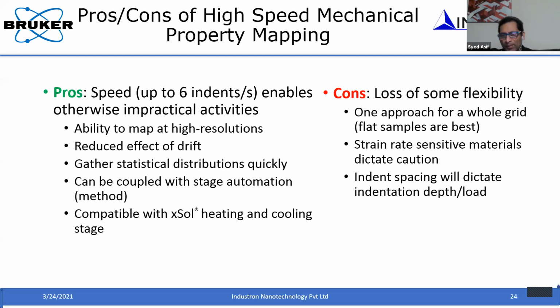So it has to be mentioned in your publication, when this kind of measurement is done, what rate of loading you are using, because some of these materials are strain rate sensitive. So that is one of the disadvantages. We can't control the strain rate, but we can control the loading rate.